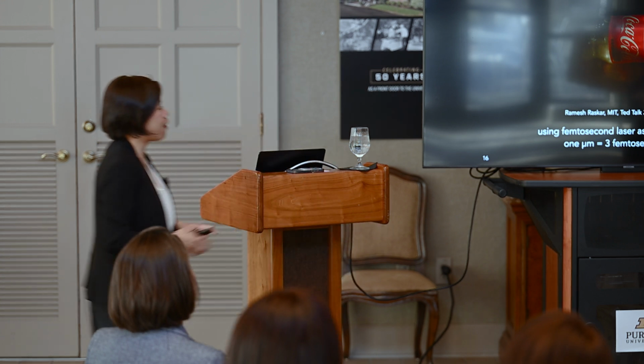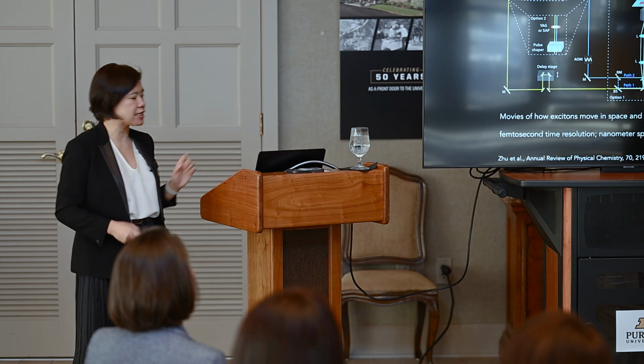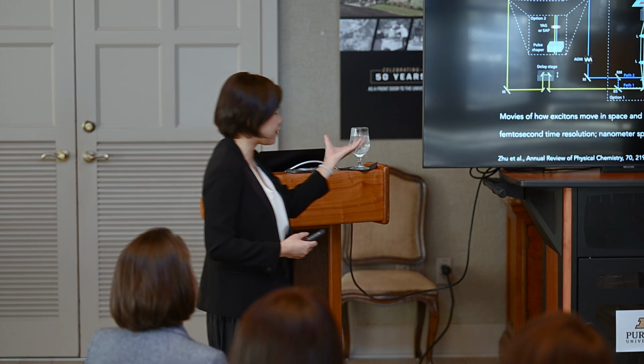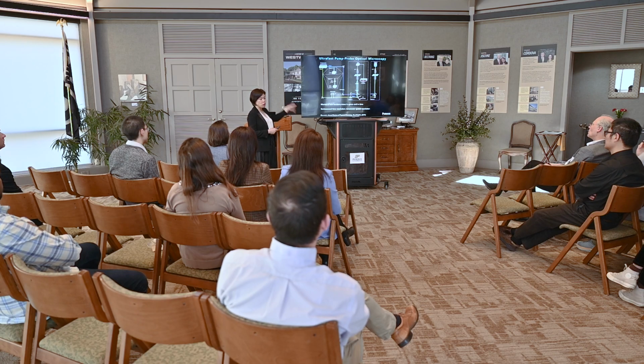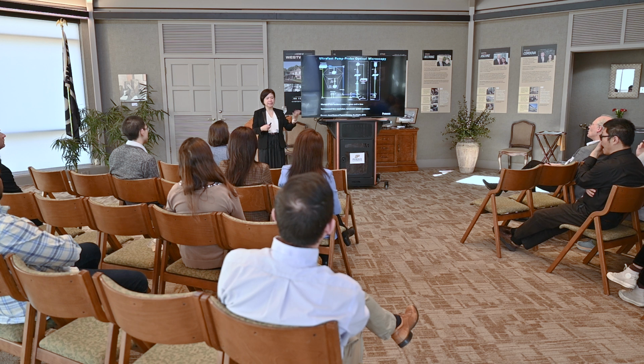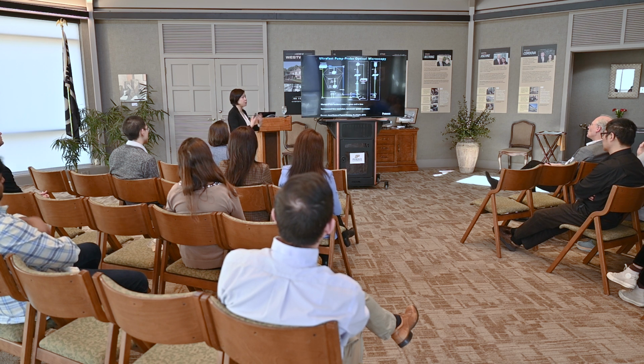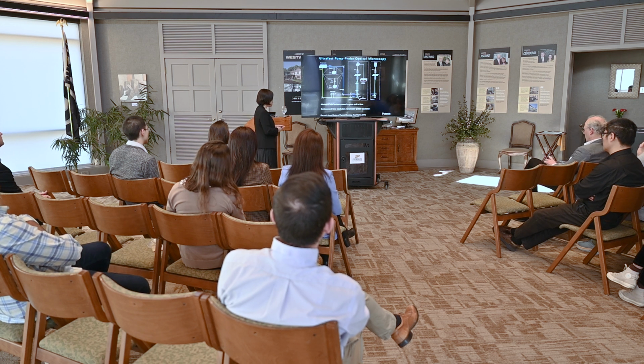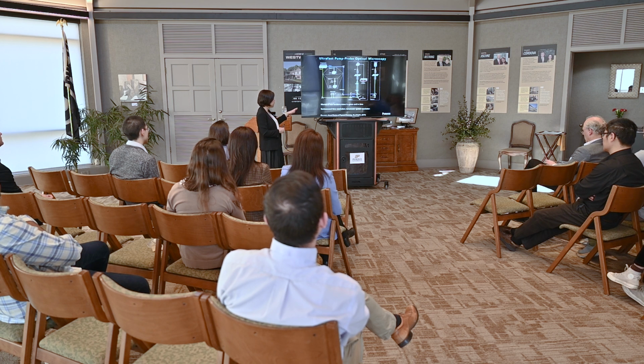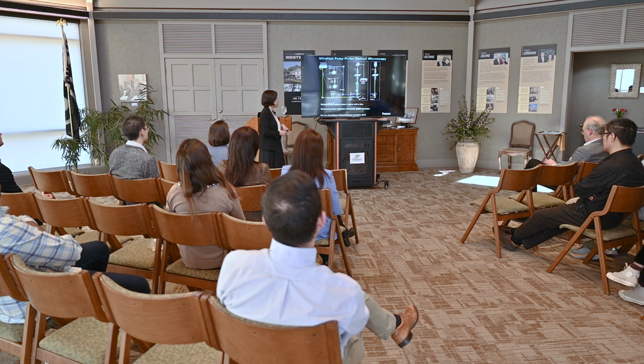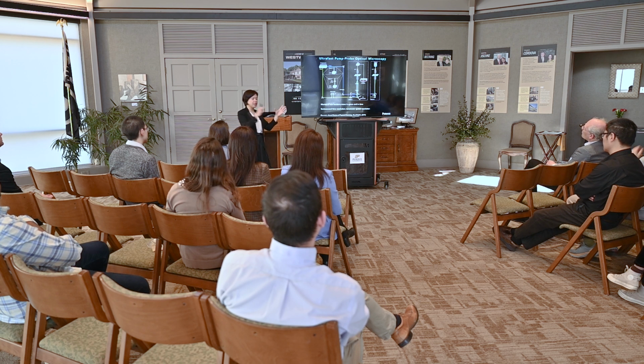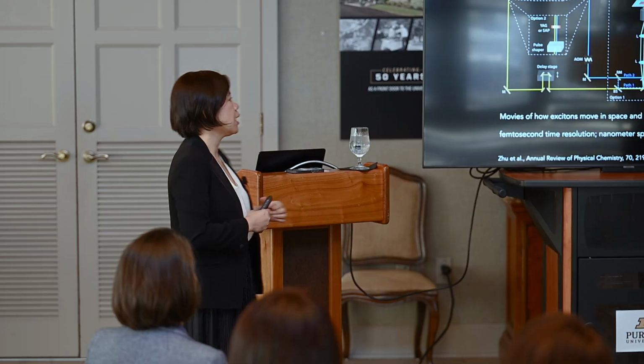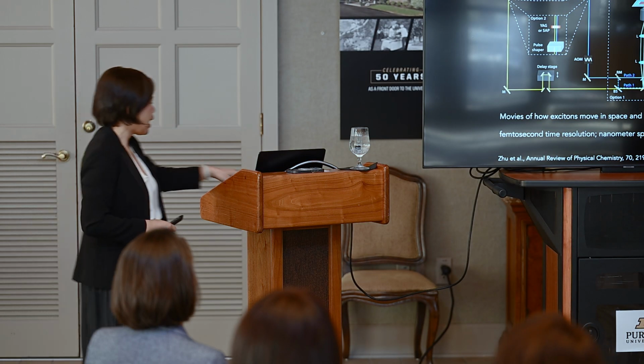And so what we do in my lab uses a similar principle, ultrafast femtosecond lasers, to image the light-generated excitons. After you use a photon to generate an exciton, what happens to those excitons? So we're looking at this light-matter interaction. Instead of just one single laser beam like in that Coca-Cola bottle movie, we have 2 laser beams. One is the light that generates the exciton, and the second acts as the shutter to track where those excitons have gone.